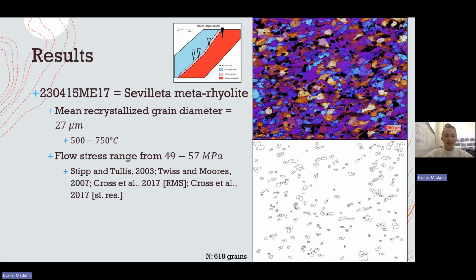And the 17 sample here is the Sevilleta meta-rhyolite, and that produced a mean recrystallized grain diameter of 27 microns. Now, this one didn't necessarily fit into any of the recrystallization mechanisms. However, the mineralogy and previous works support that this is of amphibolite facies, and that has a temperature range between 500 to 750 degrees Celsius. This had a flow stress range between 49 to 57 megapascals.